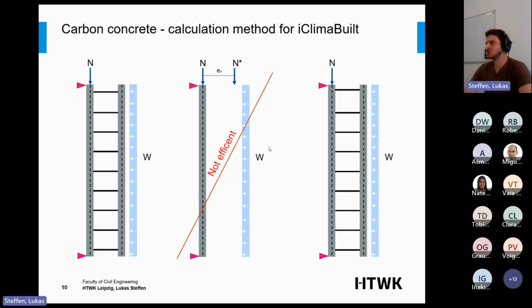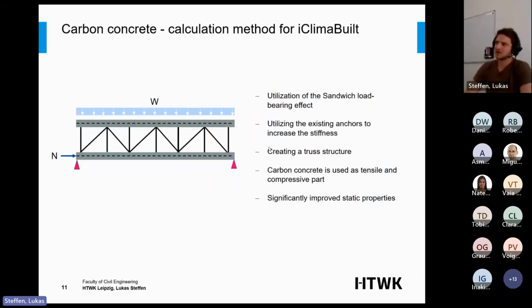As you can imagine, it's not effective to calculate it like this. A better way is to use the sandwich effect and place your anchors at a different angle. So we can build something like this one on the left side, on the right side. So you have a classic truss that we can build in. With this method, we have a new system, and now we can use both shells for load bearing. Because on both carbon concrete slabs, we can put compression forces and tensile forces, and our anchors give us spacing and stiffness for the system, so it gets much more efficient.